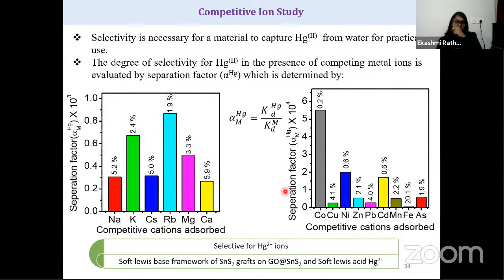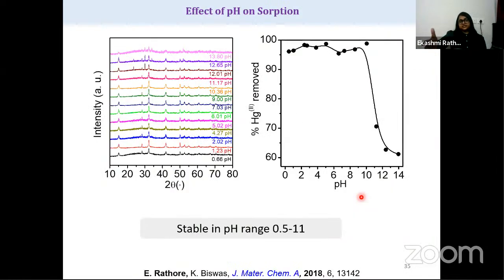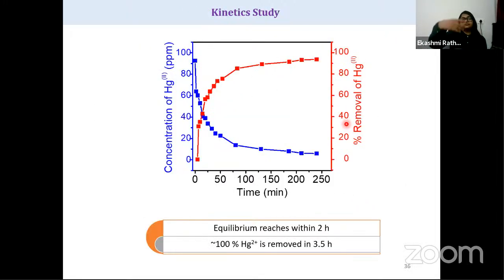Here I wanted to understand whether it binds only to mercury or to other heavy metal ions also. I tested with other heavy metal ions, and I found that it's highly selective towards mercury ions. This is due to the soft Lewis base framework of SnS2 grafted on graphene oxide and the soft Lewis acid mercury ions. Coming to the pH study, we found that the material is stable from pH 0.5 to 11, and more than 90% of the mercury could be captured. We then performed kinetic studies, and found that it reaches equilibrium within 2 hours, and 100% mercury removal could be obtained within 3.5 hours.